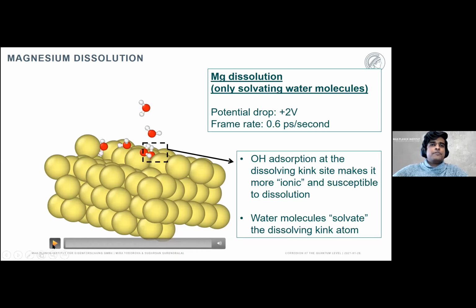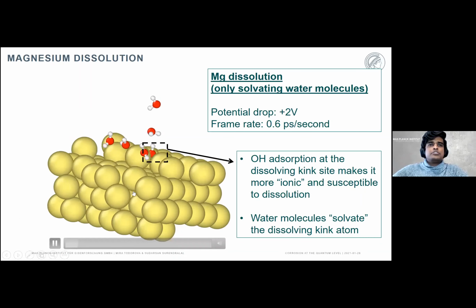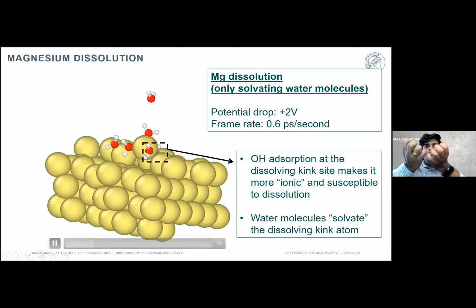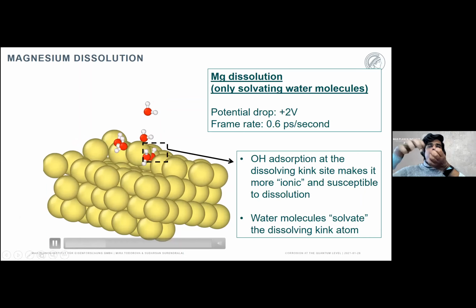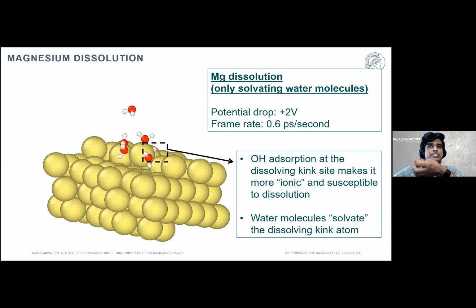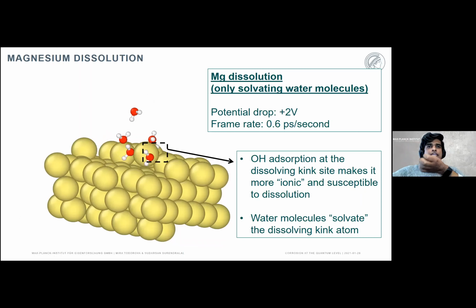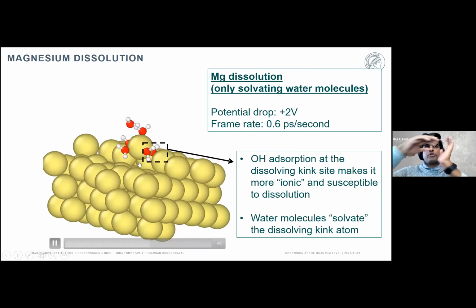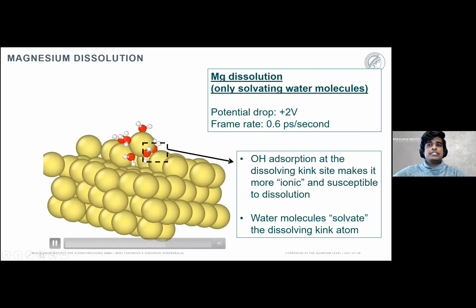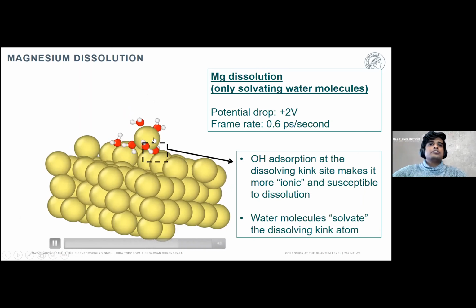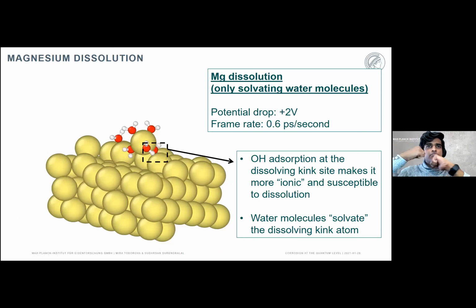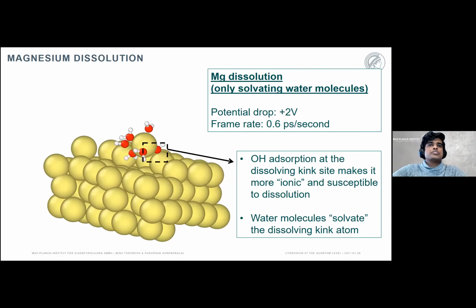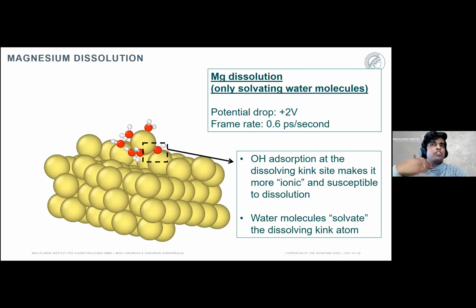And so once the dissolution process starts, what happens is that this kink site is already a little bit ionic. And once the potential is applied, it's able to break its bond and then form a solvation shell with the water molecules surrounding it. And so this is basically how the beginning, the very fundamental step of the dissolution process in magnesium occurs. And all this has been done using the potentiostat scheme, which allows us to accelerate such reactions.